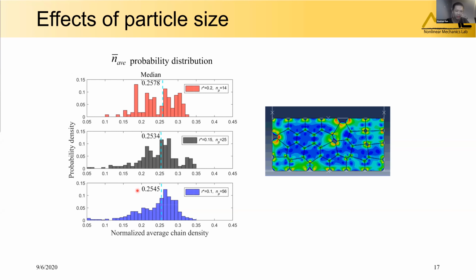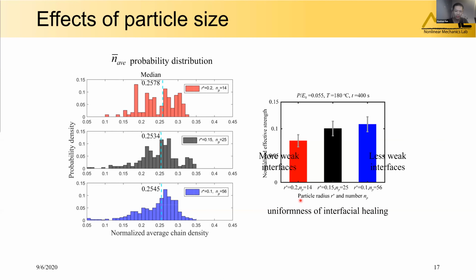But the variation in this chain density can explain it. For the smaller particles, the interfacial chain density is more concentrated to the median value, meaning most interfaces have a similar healing extent, and there are few weak interfaces. While for the larger particle cases, the chain density is more randomly distributed in a wide range, meaning there are more weak interfaces that can facilitate the structure failure and lower the strength. So therefore, the strength is governed by the uniformness of the interfacial healing degree when the median is similar.